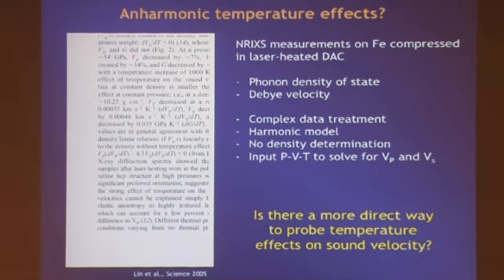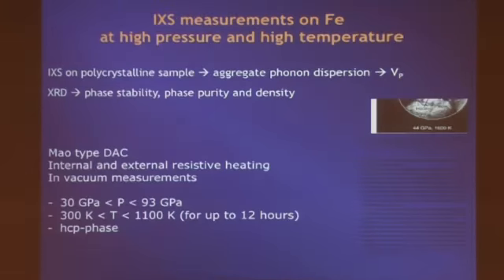However, the complex data treatment involved, and the high reliance on external PVT equation of state, which in the case of iron are particularly critical because different studies do not agree completely, bring doubt on the validity of this result. Furthermore, there has not been any density or phase determination during this measurement, and another argument that was brought up was that the analysis for this data involved a harmonic model to ultimately argue for non-harmonic approximation. So we asked ourselves if there was a more direct way to probe temperature effect on sound velocity, and at least for VP, the answer is yes.